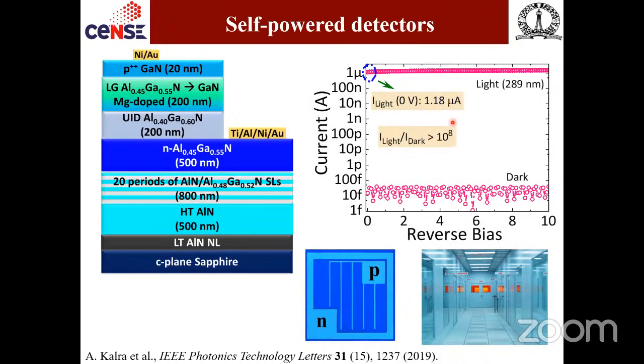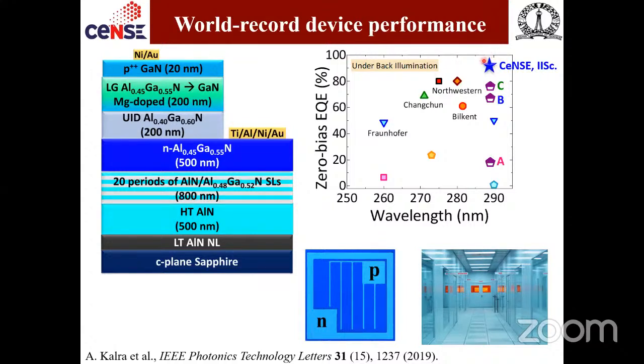I will pause here just for a bit, where I would like to highlight the key result that me and the previous speaker could achieve. Here you have this complicated architecture of photodetector, but what we could achieve was that even at zero applied bias, we could get a light to dark current ratio of 10 to the 8, which means that if you do not have any radiation on your detector, you record femtoamperes of current, but as soon as you shine UV light, you measure microamperes of current, making this one of the most sensitive detectors which has ever been developed. And the efficiency was found to be 92% for these detectors, which is the world record for such photodetectors.